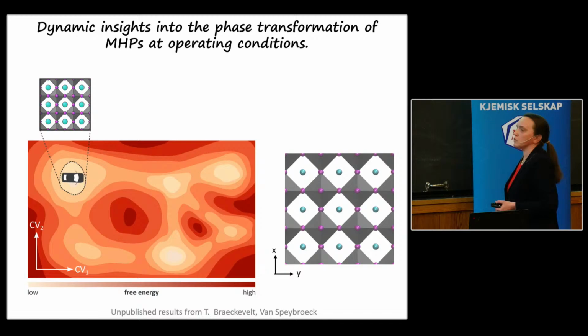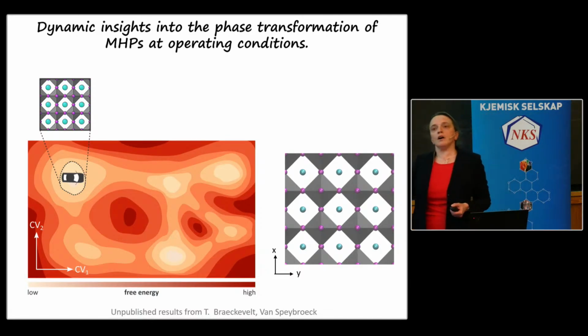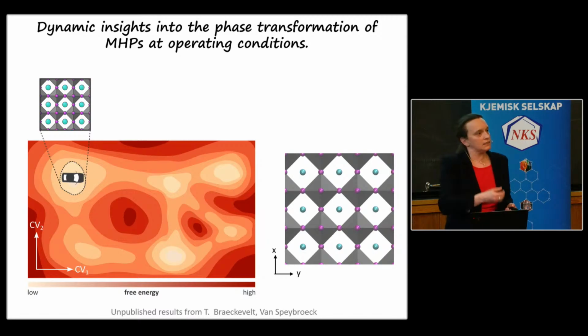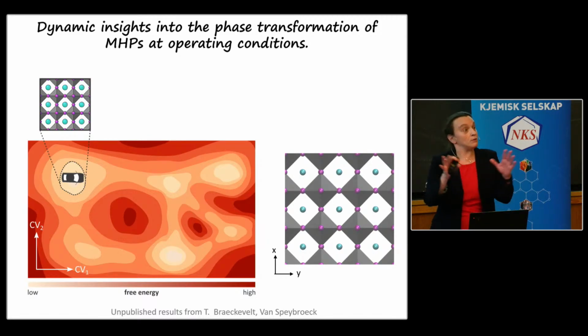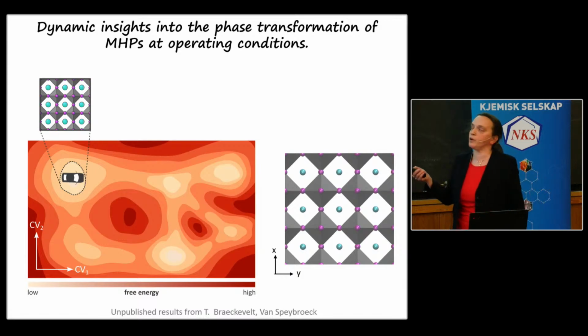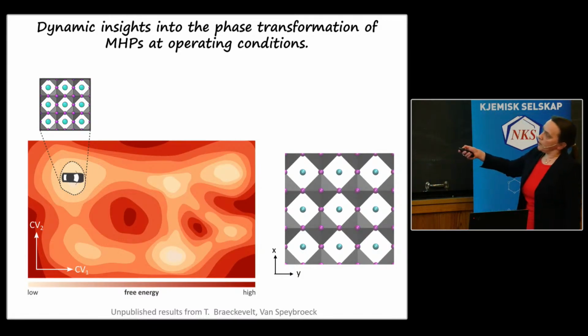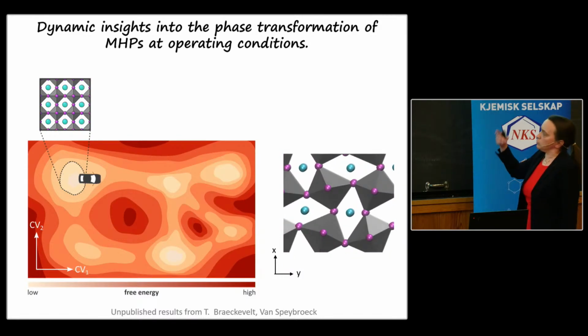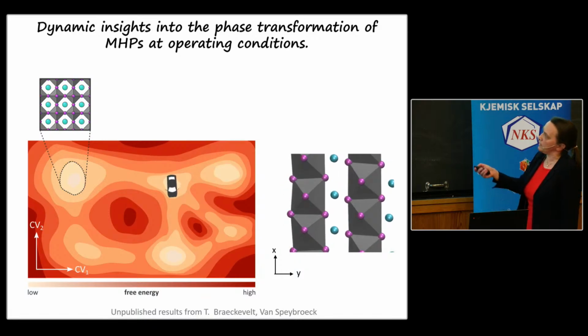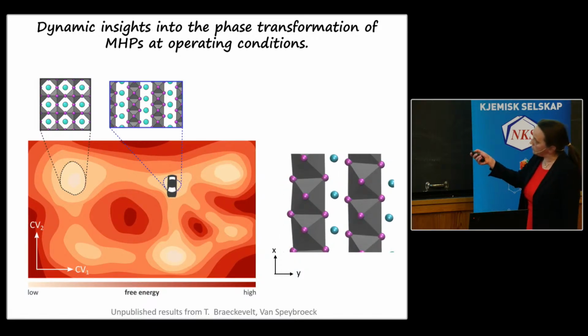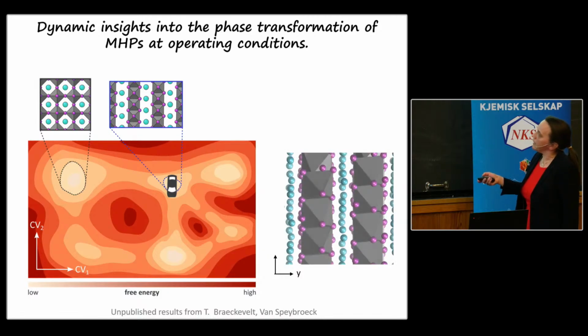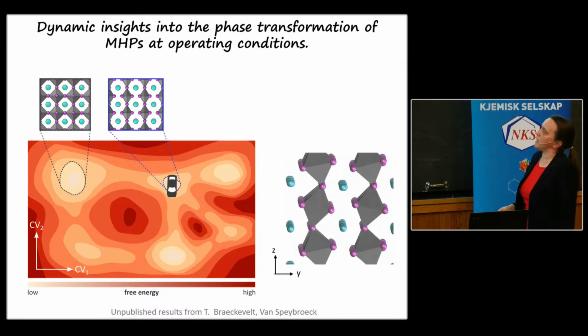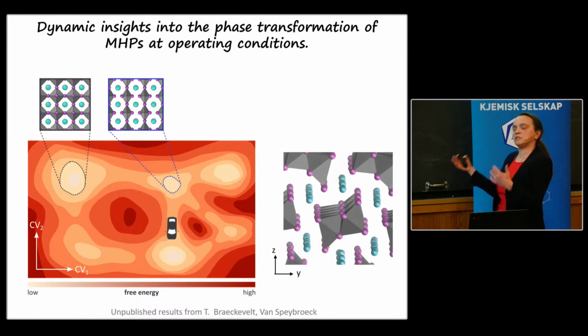And that is the reason why we also thought maybe we have to also try to construct this free energy landscape, let's say. So this mountain hiking map that I also referred to earlier. So basically we start here from this nicely ordered structure, so the active phase. And then we can start to do some MD simulations, and then we can see that first we have a first movement where these units are displaced like this, and we have these arrangements like this. It does not go in one step. And then we do another molecular dynamics simulation, and finally it goes to this disordered phase.